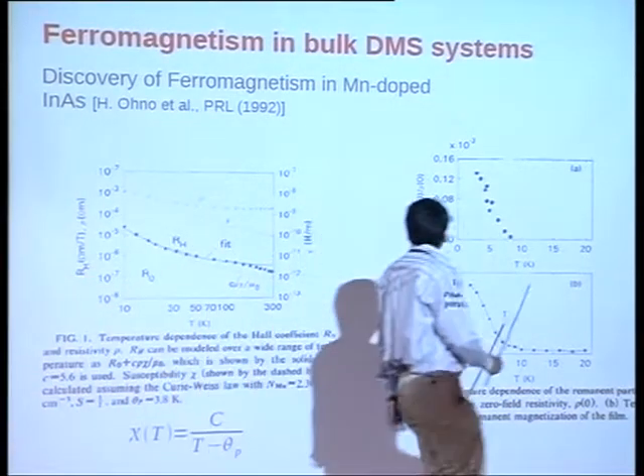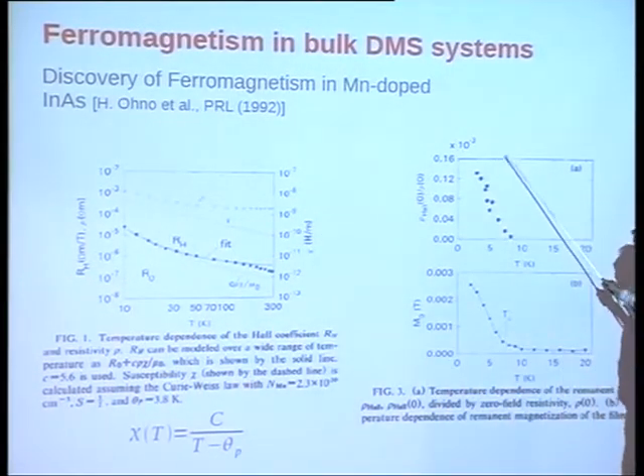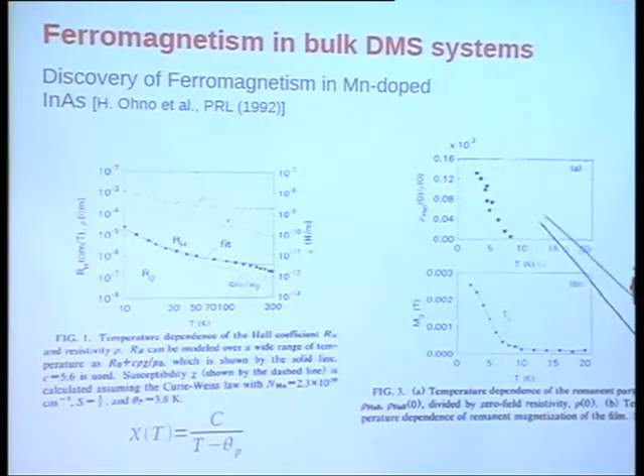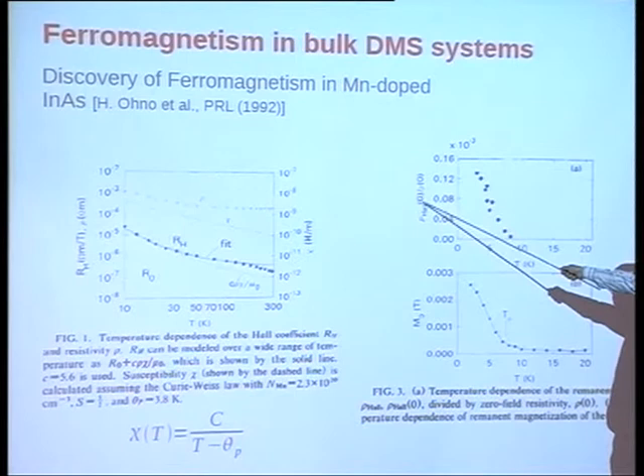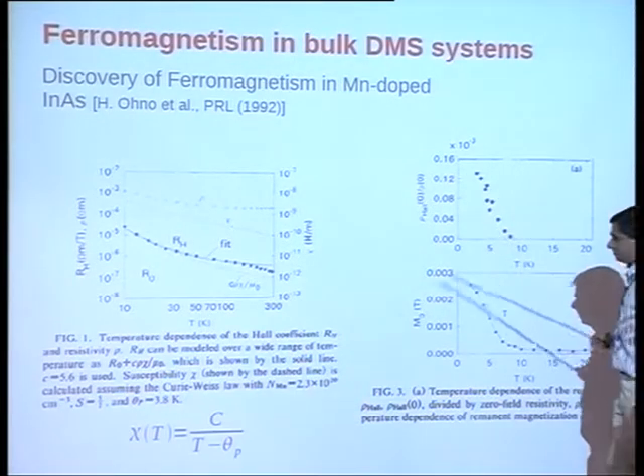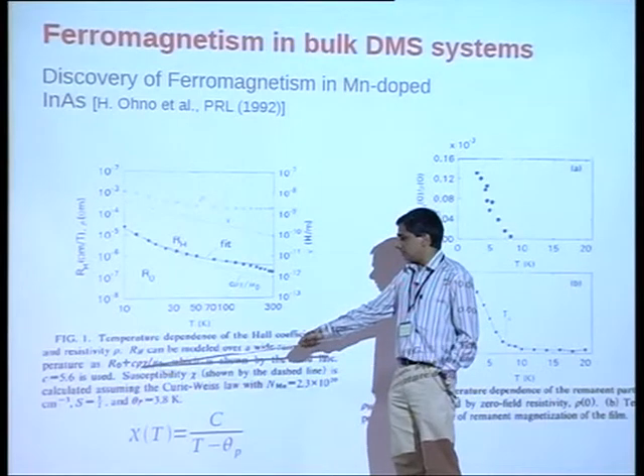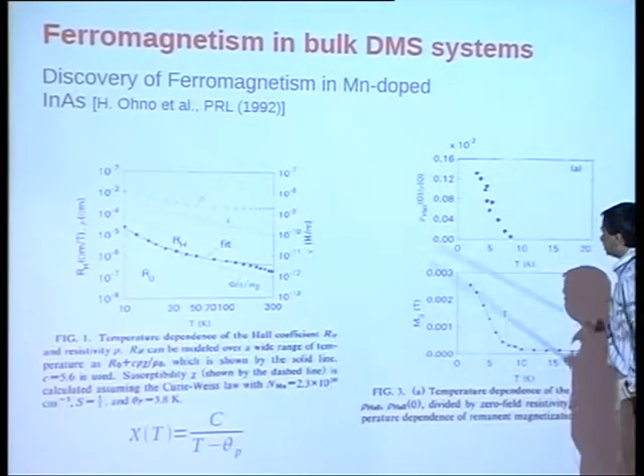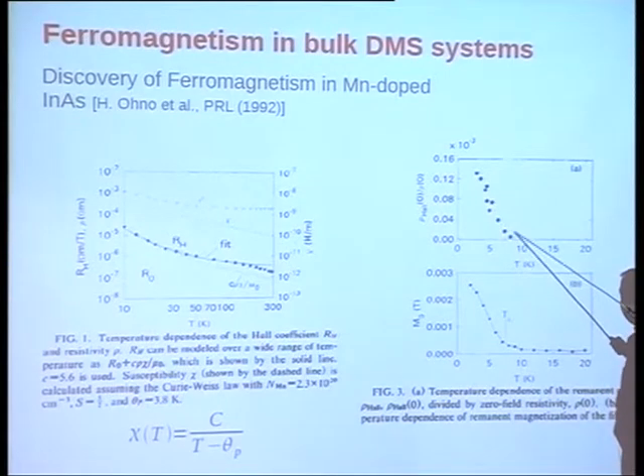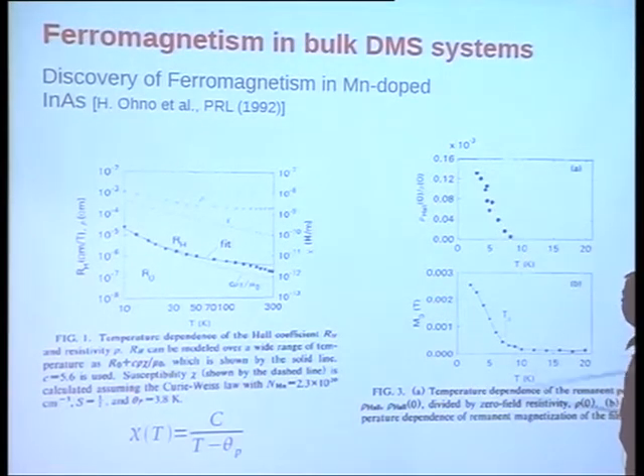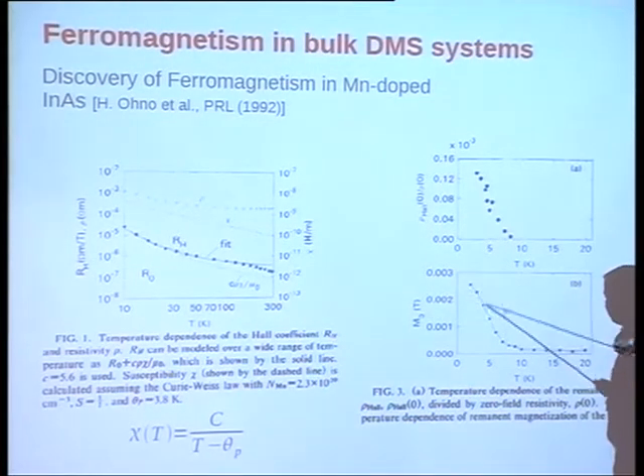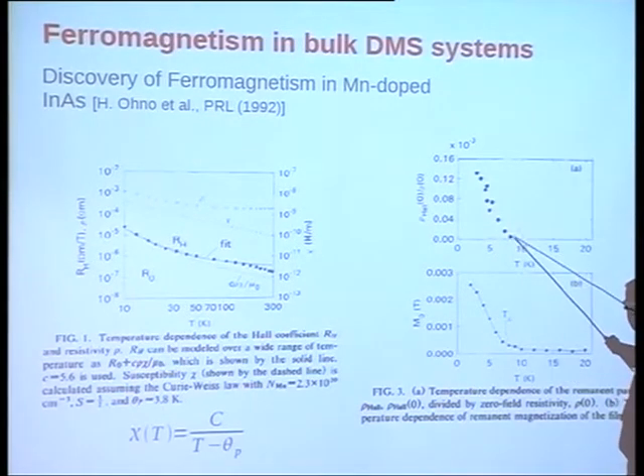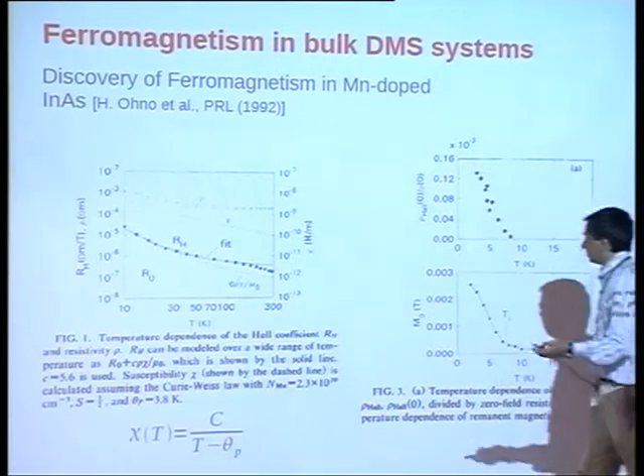And this is another set of plots from the same paper. It shows the remnant Hall effect. As you turn off the magnetic field, you still have some Hall constant left. That's coming from magnetization here. So this is the anomalous part then showing up, and the remnant part survives up till about 7 or 8 kelvins. And here is a direct measurement of magnetization, also showing a comparable sort of onset. So this is also the remnant magnetization as a function of temperature, and shows a similar temperature scale for emergence.